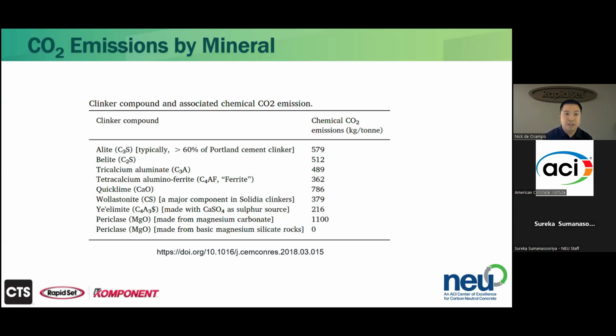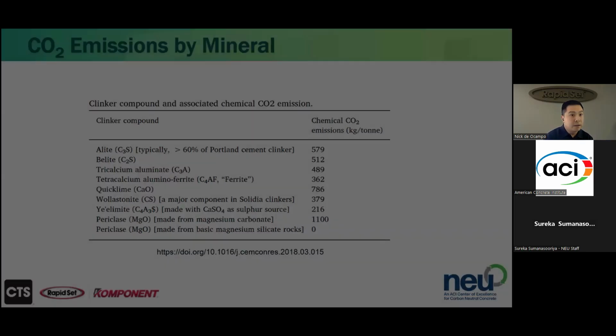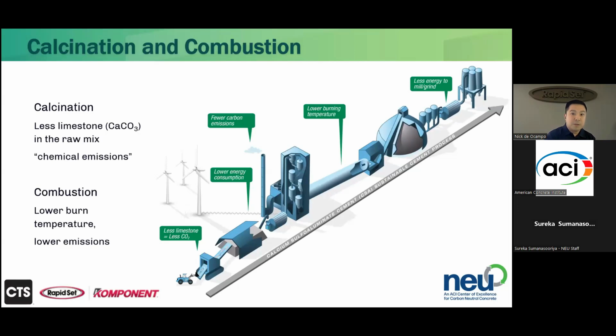That only emits 216 kilograms of carbon dioxide per ton of yeelimite produced. And the reason for that is it simply requires less limestone in the kiln. So the chemical emissions are from the separation of calcium from the carbon and oxygen in limestone, whose chemical formula is CaCO3.